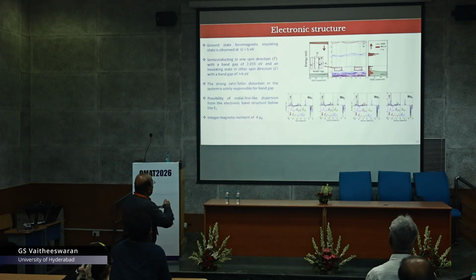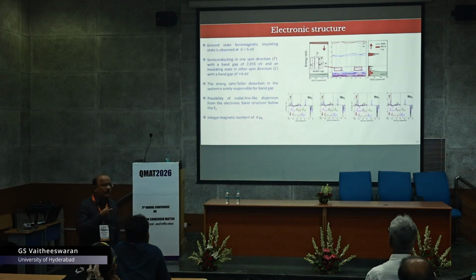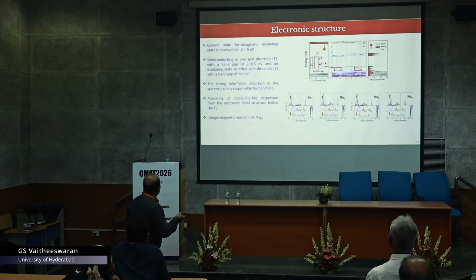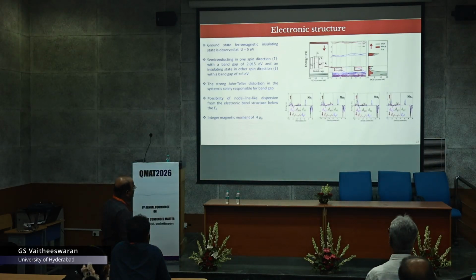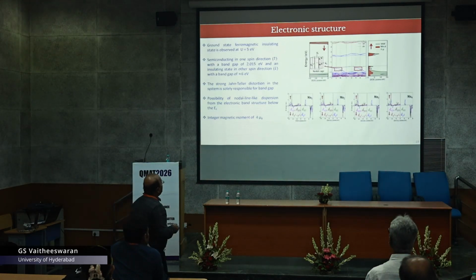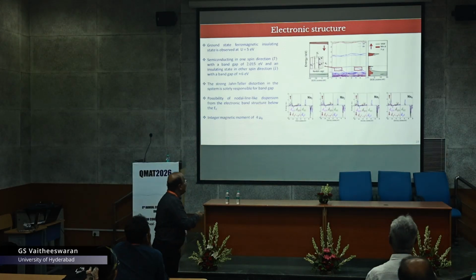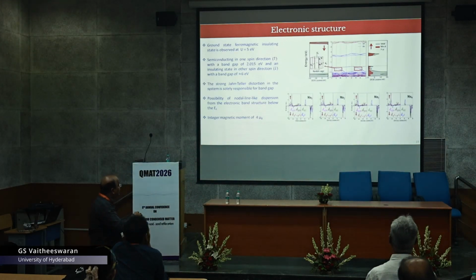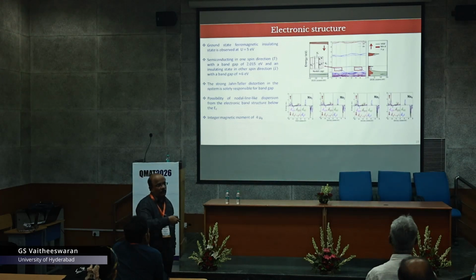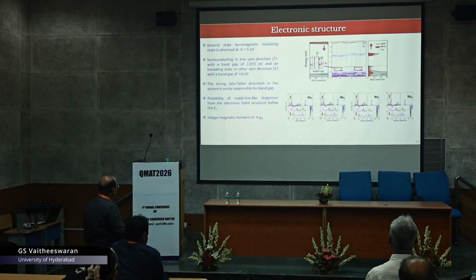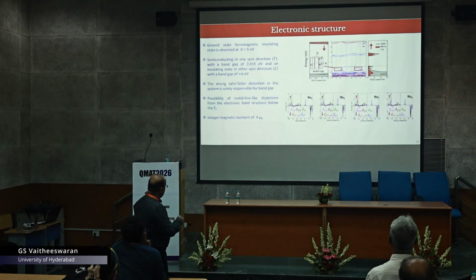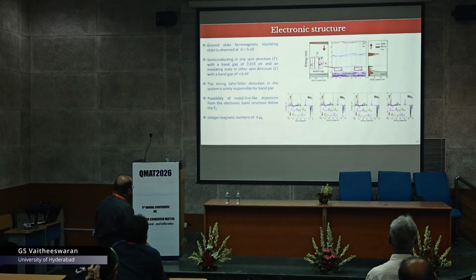As a next step, we also tried to understand the electronic structure because this is a semiconducting system, and we do get the gap in both the spin up and spin down channels. Interestingly, we also see a nodal-line-like behavior in the states just below the Fermi level, although it's not interesting because the system is actually gapped. The total magnetic moment is around 4 Bohr magneton, which is quite good compared with the experiments, and there is a possibility of nodal line like dispersion from the electronic band structure.